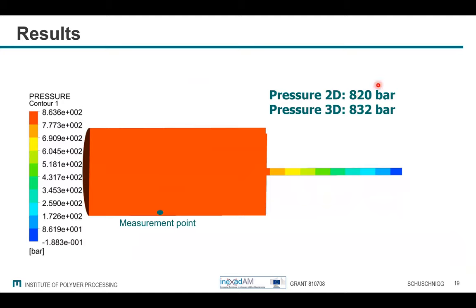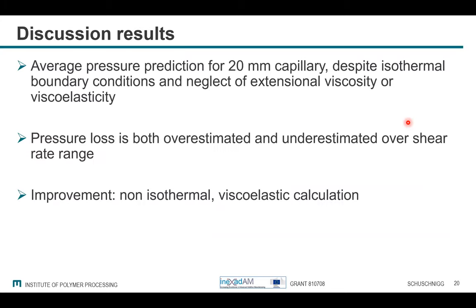The 2D pressure loss was 820 bar simulated, and the 3D 832 bar, and the measured pressure was 893 bar. So it was not the best prediction for the 20 millimeter capillary, because there is the possibility that I ignored non-isothermal conditions, and I neglected extensional viscosity or elasticity in this case. The pressure loss over different flow rates was either overestimated or underestimated. So we can really see that there are different things here where we can improve, for example, non-isothermal or viscoelastic calculations.